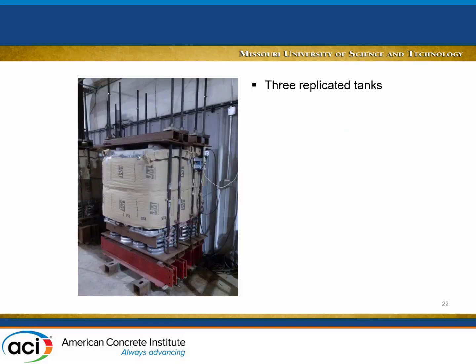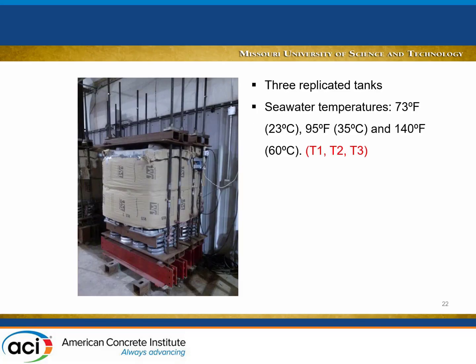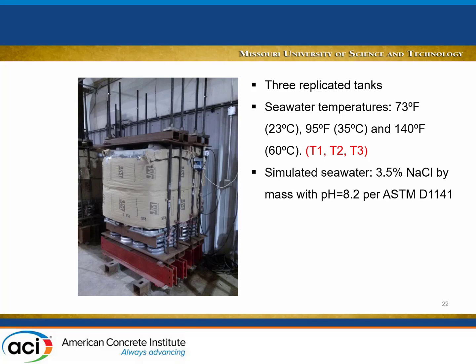So as I mentioned, we have 3 replica tanks at different temperatures, 73, 95, and 140. We have 3.5% sodium chloride, and the pH was about 8. And then we take the specimens out at 90, 200, 300, and 450 days. So it's roughly slightly more than a year.